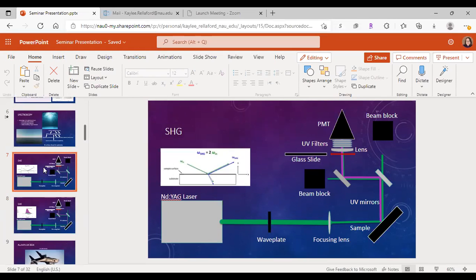If the surface isn't polished, then you'll have a lot of non-specular reflection or scattering of the light, right? So are your optics such that you're trying to collect all the ultraviolet, all the second harmonic generated light, regardless of the angle it comes out, or are you just selecting the specular? Because we're using a PMT, it's everything that can get in there. We do find that polished samples reflect a whole lot more specularly than our unpolished do. So it's a lot easier to get all of the signal that we can from the polished samples.